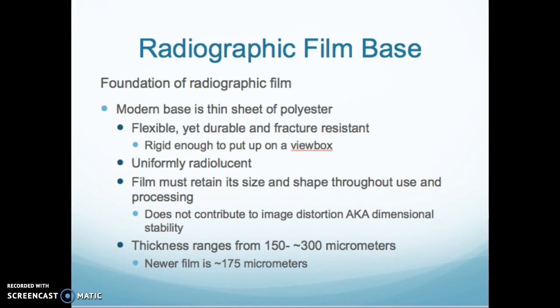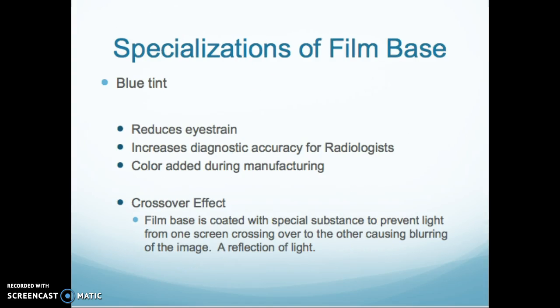With the film base, it's polyester, like I talked about. It's flexible yet durable, and it's strong enough for us to be able to pop in a view box. It's uniformly radiolucent, that's very important, and film must retain its size and shape throughout the use and processing. So we call that dimensionally stable. The thickness ranges anywhere from 150 to 300 micrometers, and the newer films are about 175 micrometers. They add a blue tint as it reduces the eye strain for the radiologist and helps with the accuracy. So the color is added during manufacturing.